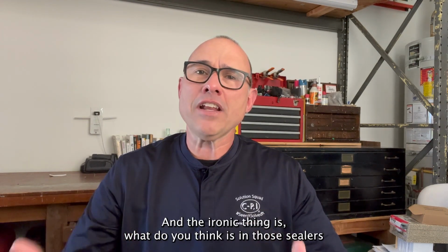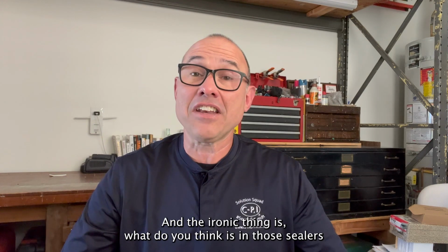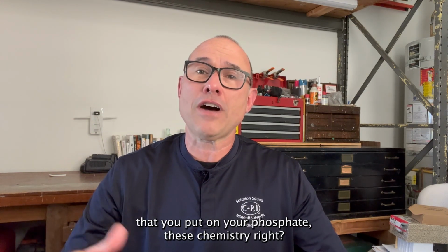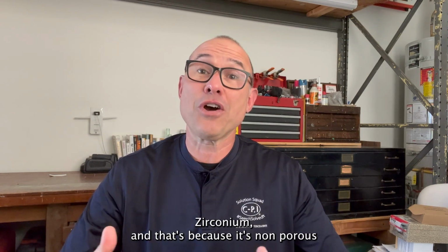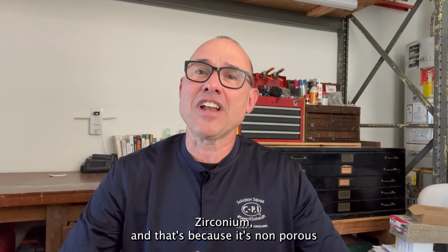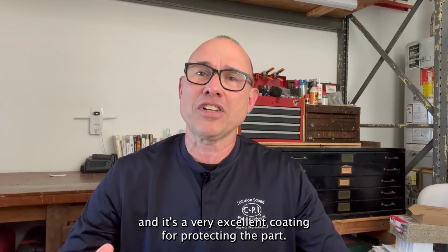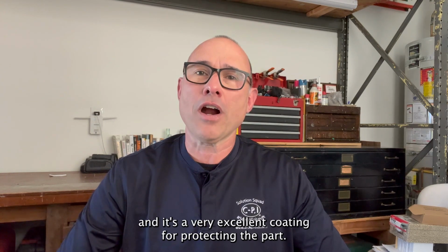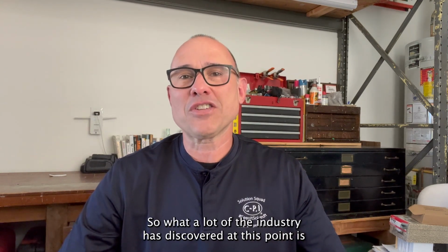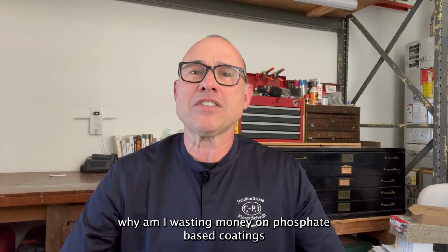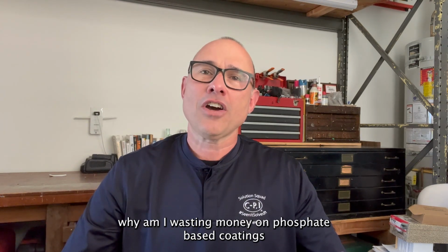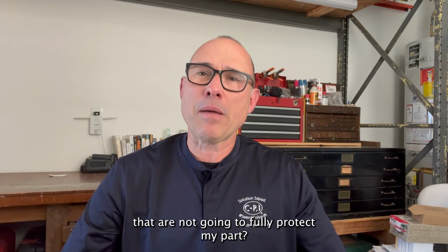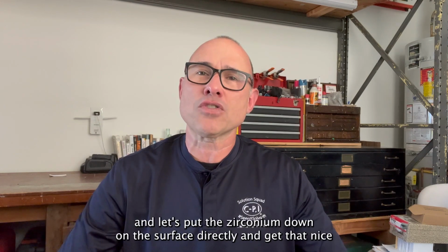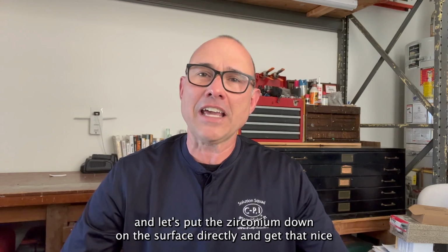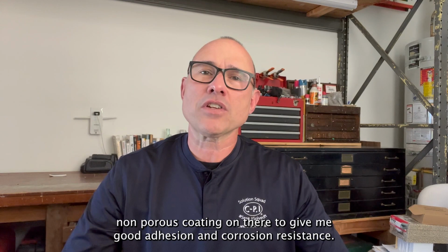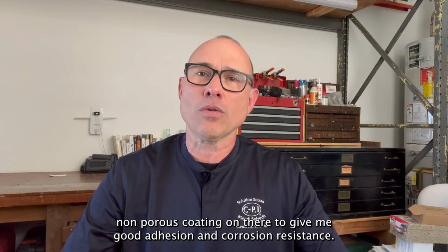And the ironic thing is, what do you think is in those sealers that you put on your phosphate-based chemistry? Right, zirconium. And that's because it's non-porous and it's a very excellent coating for protecting the part. So what a lot of the industry has discovered at this point is, why am I wasting money on phosphate-based coatings that are not going to fully protect my part? Let's just skip that and put zirconium down on the surface directly and get that nice non-porous coating on there to give me good adhesion and corrosion resistance.